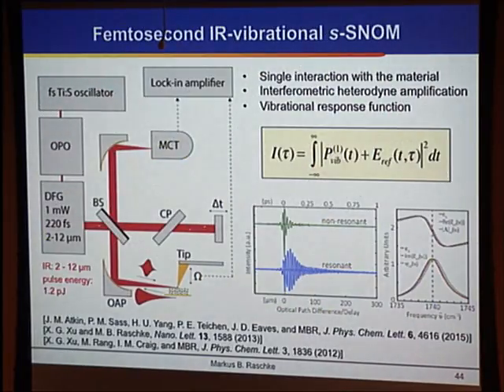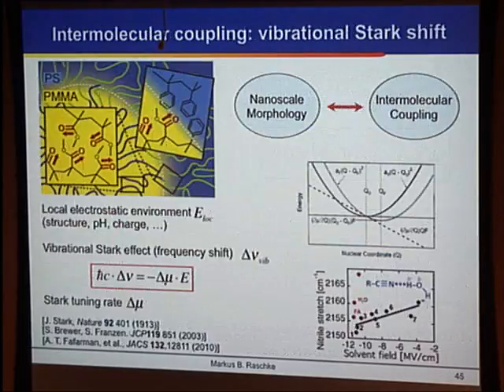So the way we do the spectroscopy here is a sort of heterodyne amplification of this near-field signal. We generate broadband, broadly tunable short infrared pulses, which are shining under the tip, and then we have a split-off component of that field, which heterodyne amplifies this near-field signal. The result is something analogous to infrared ellipsometry. We measure phase and amplitude of the local spectroscopic response of the material under the tip.